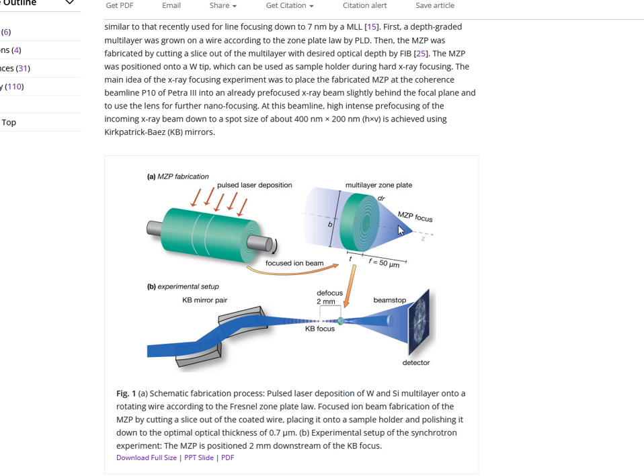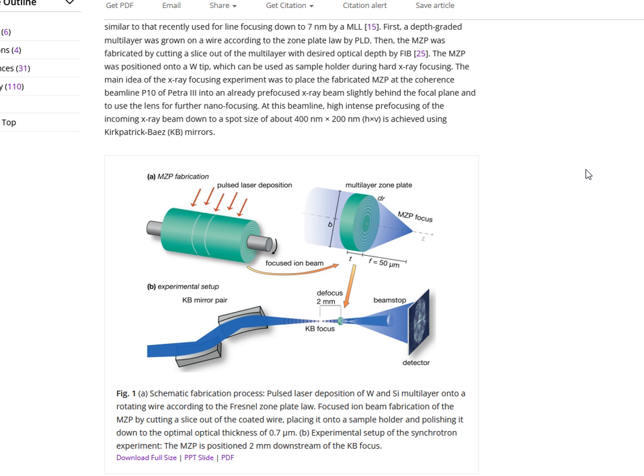The so-called zones here, those circular rings, have to be thinnest at the most outside position, and there only a few nanometers are reached. The homogeneity and the precision of those layers are responsible then for the resolution of this optical component. And here in this paper we reached focusing in 2 dimensions of below 5 nanometers. That is, at least to my knowledge, still the record for hard X-ray focusing. So this precision can be reached using the PLD setup.